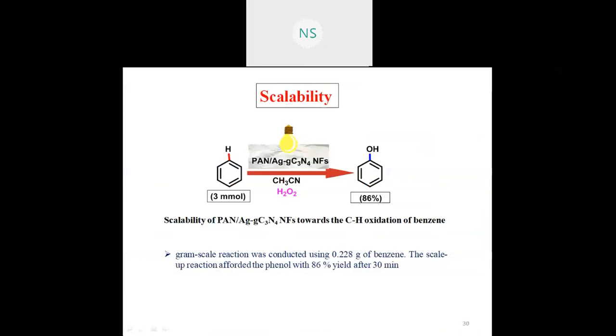So there is a scalability we have done. Scalability of PAN/Ag-gC3N4 towards the CH oxidation of benzene we have done. And that can be used up to the fourth to fifth cycle. The same catalyst can be used from the first cycle to the fifth cycle. If we wash it properly, again we can regenerate, and that catalyst can be used continuously up to the fifth to sixth cycle.